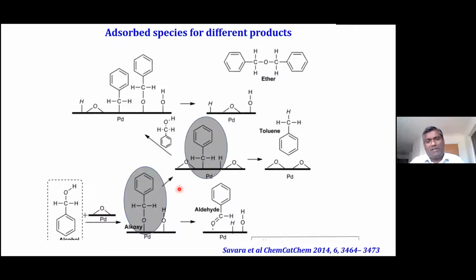So this is an example where, by tuning the metal support interfacial site, we can tune the selectivity of a reaction. And another parallel concept is that for production of benzaldehyde, this kind of adsorbed species is needed. So for getting this kind of alkoxy species, a basic support is necessary. When you have a basic support, it deprotonates the alcohol to form this alkoxide species that adsorbs on the palladium site, and you can have the oxidative dehydrogenation reaction. So that's the rationale behind choosing basic supports for this particular reaction.